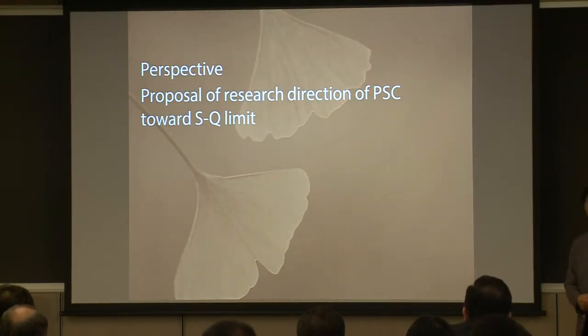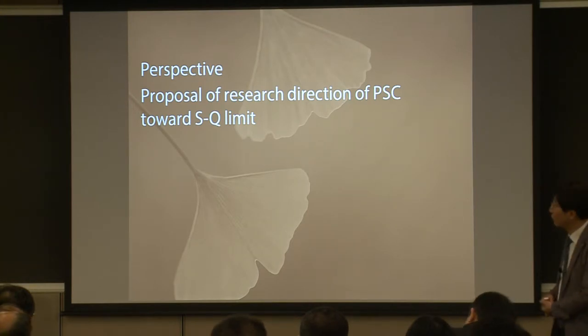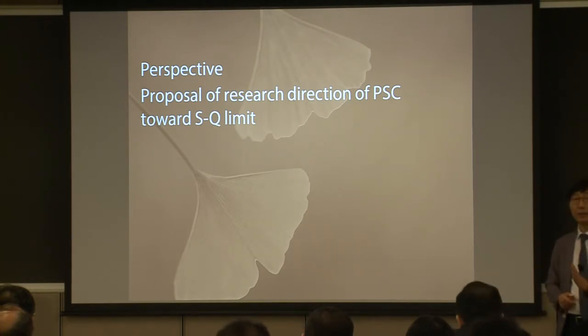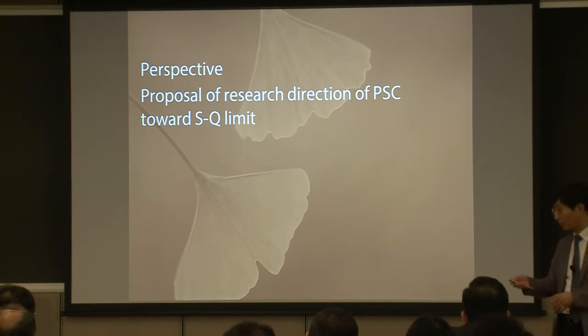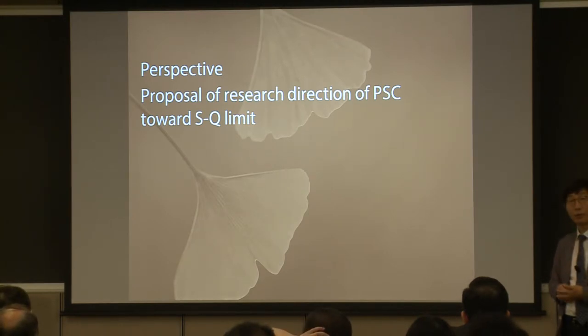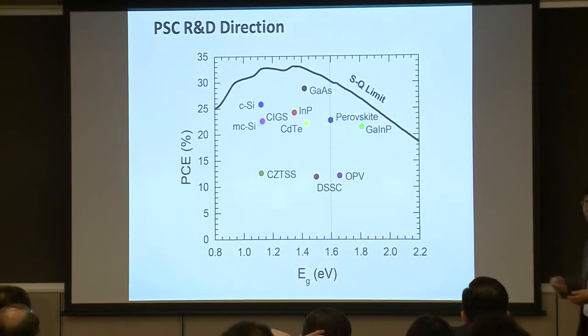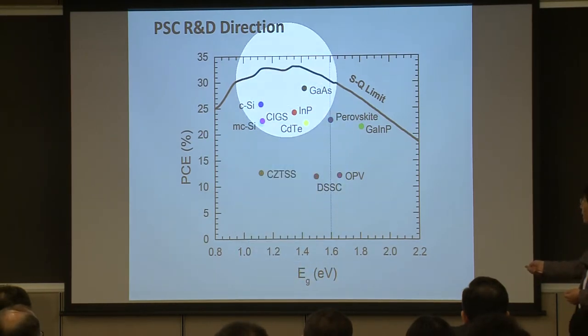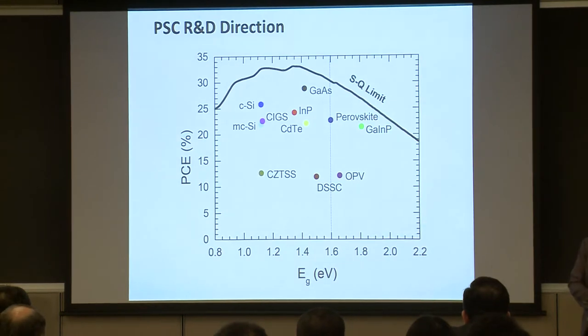And finally, I'd like to mention the research direction of the perovskite solar cell. So in terms of the Shockley-Queisser limit, if you think about the band gap energy of about 1.6 eV for a perovskite material, then the theoretical efficiency will be about 30%. For instance, gallium arsenide with 1.4 electron volt band gap energy, the maximum efficiency will be about 33%.